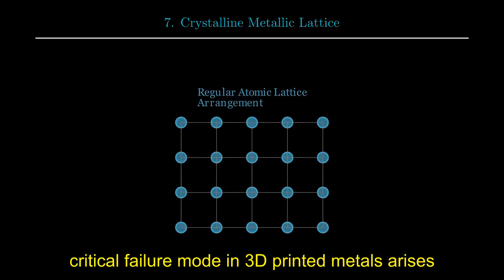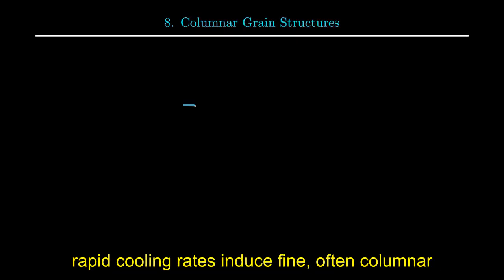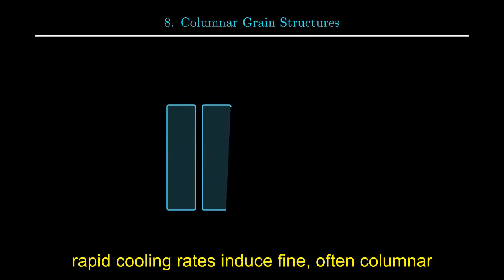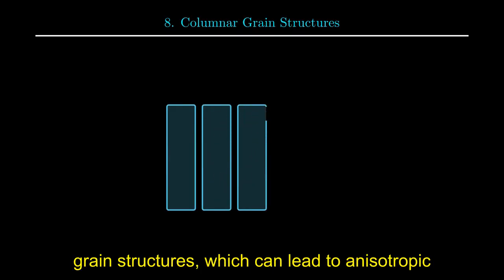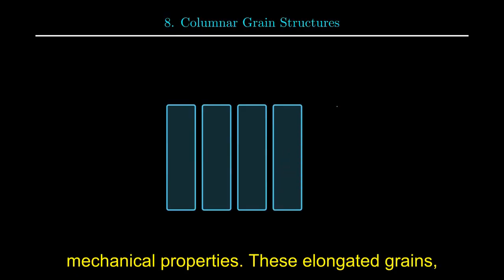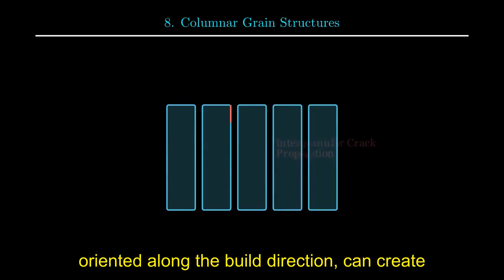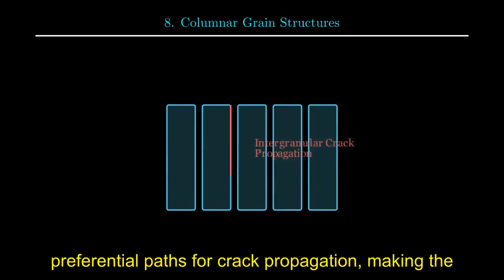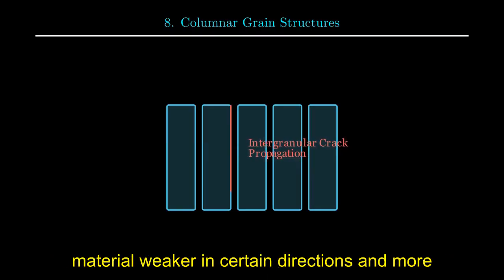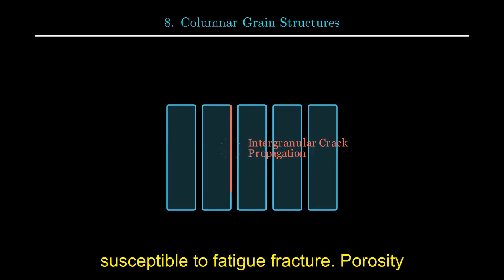One critical failure mode in 3D printed metals arises from their distinctive microstructure. The extremely rapid cooling rates induce fine, often columnar grain structures, which can lead to anisotropic mechanical properties. These elongated grains, oriented along the build direction, can create preferential paths for crack propagation, making the material weaker in certain directions and more susceptible to fatigue fracture.